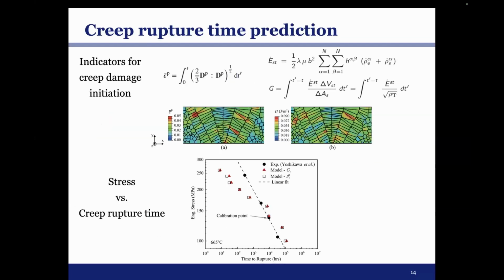And also based on the same model, we can do something more. For example, we would like to predict the creep rupture time. And there are, of course, many ways to do that. We do it simply by introducing some indicators. One is cumulative plastic strain, another one is a dislocation density based indicator. And we need to use one experiment data point to calibrate the critical value of these indicators, and we try to predict the others. As we can see here, what we have obtained is that there is a good agreement for lower stress levels, but some discrepancy has been observed for higher stress levels, probably because there are some more physical mechanisms that we haven't considered.